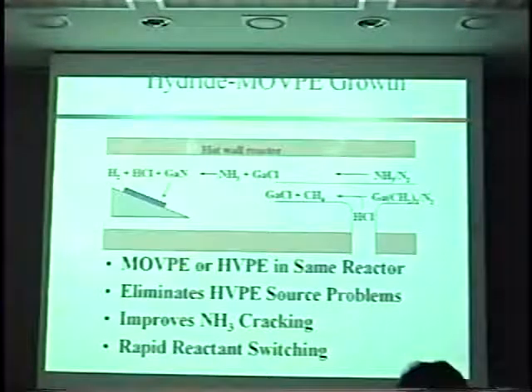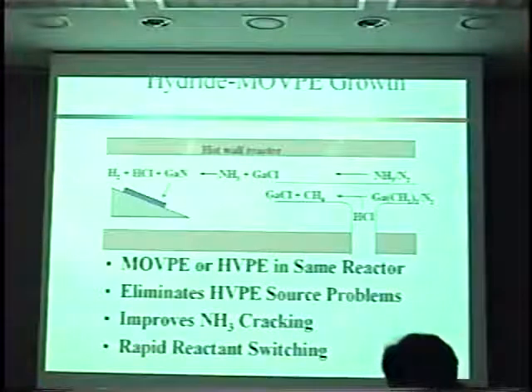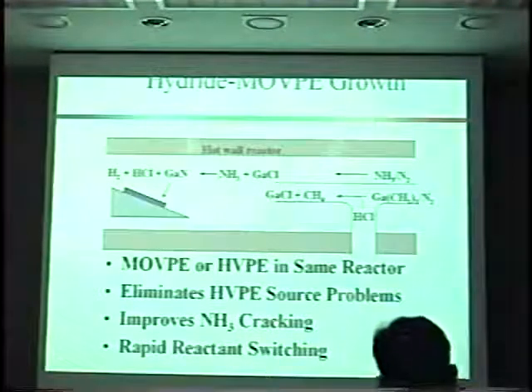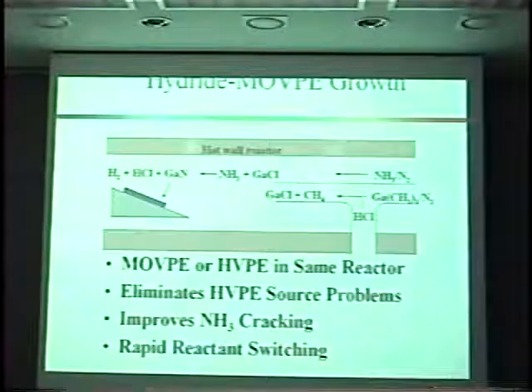In traditional hydride VPE, we take HCl, pass it over liquid gallium to form gallium monochloride, and use the hydride ammonia as your precursors for CVD. We combined MOCVD with hydride VPE in the sense that we took trimethyl gallium, which is an organometallic, reacted it upstream with HCl to form the gallium chloride in a hot wall reactor, and then in the deposition zone, it looked like a hydride reactor. In the source zone, it looks like an MOCVD system. And so we combine the best of both designs.